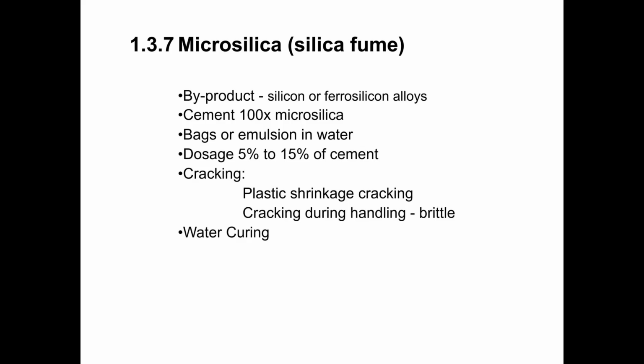There are some drawbacks to using microsilica. It is such a fine material that it increases the surface area of the particles within your concrete to the point that it's very difficult to have enough water and cement slurry to coat all of the particles. And so the surface of the concrete tends to dry out quickly because you don't have much of any bleed water. So there's an increased potential for plastic shrinkage cracking when using silica fume.